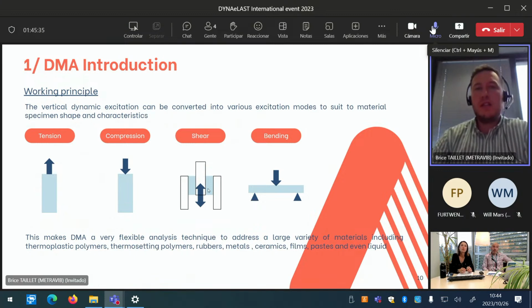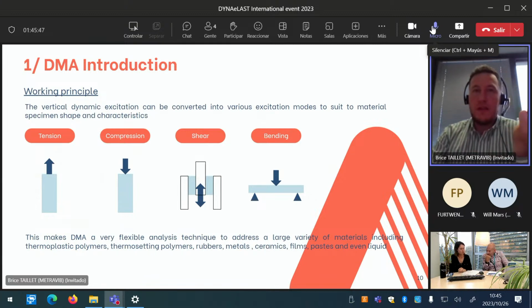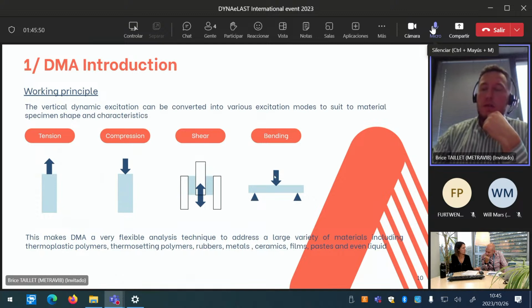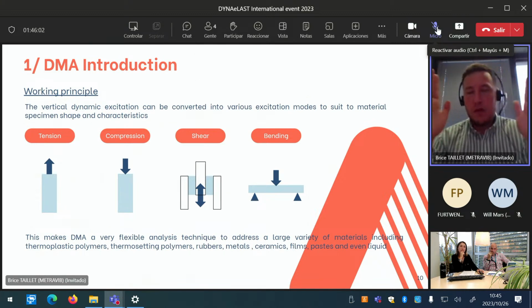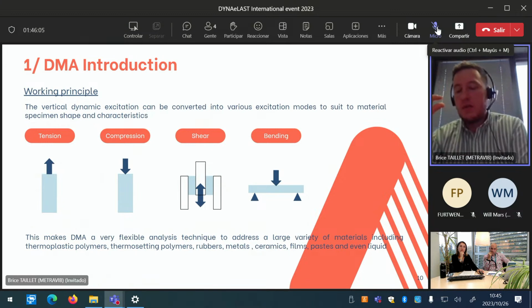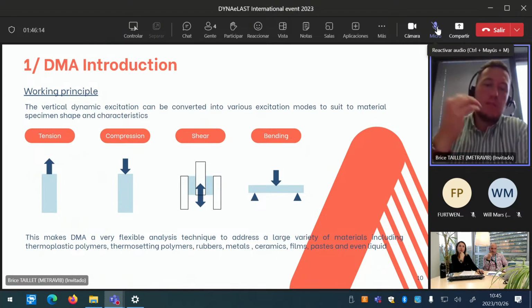For shear excitation mode, it's really easy because we use paste materials. Diameter is 10 millimeters, and the thickness is about 2 to 3 millimeters. And in bending mode for TPE, TPU, or composite materials, we are able to work with large specimens up to 130 millimeters wide, with a thickness of a few millimeters up to 10 millimeters. But we have to be careful to be representative between a specimen and the material in its common use.